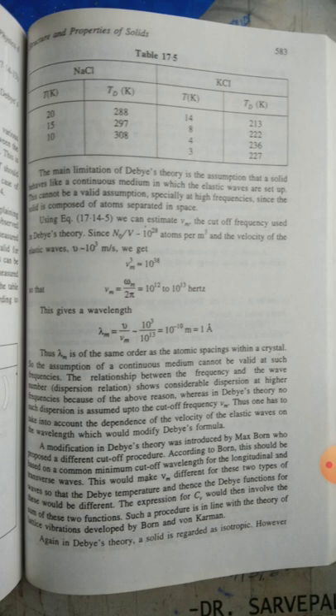A modification of Debye theory was introduced by Max Born, who proposed a different cutoff procedure. According to Born, this should be based on a common minimum cutoff wavelength for the longitudinal and transverse waves. This would make νm different for those two types of waves, so that the Debye temperatures and the Debye functions for them would be different. The expression for CV would then involve the sum of the two functions. Such a procedure is in line with the theory of lattice vibrations developed by Born and von Karman.